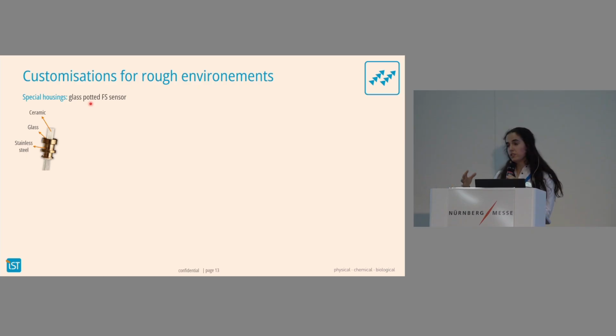And in that sense, we wanted to present here two examples. One is this glass-sealed FS sensor. So what we have here is a ceramic sensor. This round part is a stainless steel housing, and the only material that we use to stick the stainless steel to the ceramic sensor is glass. This gives a quite robust or elegant solution because this allows to directly install it in the final application.